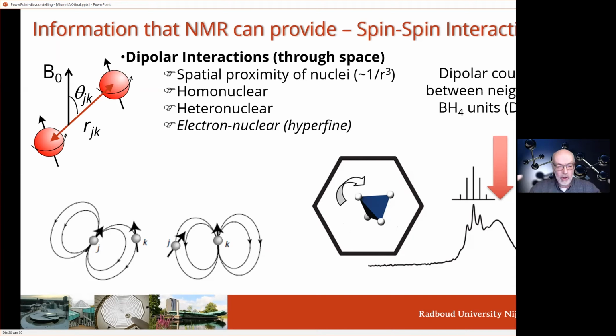But in a well-organized solid, where all the BH4 sit in a crystal lattice, still the protons of neighboring BH4 units couple to a given boron. That gives us this line width, and we can exactly predict that. So we call this the dipolar interaction. And actually that allows us to even measure distances between nuclei. So you can get very detailed information about the distance between different neighboring nuclei. And it's super accurate because it depends on the inverse of the third power of the distance.